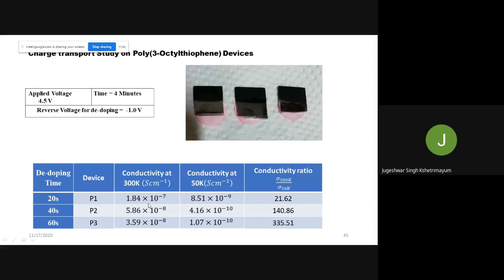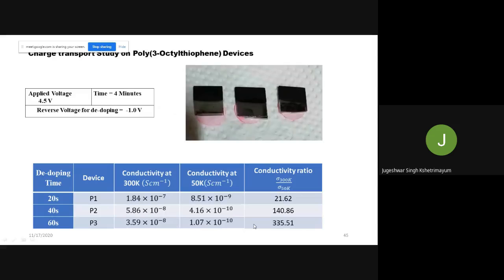Now when I look at the conductivity ratio for P1 from 300 Kelvin to 50 Kelvin, the ratio is 21.62. The variation of conductivity is very small compared to the others. But in the case of P3, the variation of conductivity is very, very high. So what does this mean? This says that a thermally activated process is already involved, which is what we are guessing. Okay, my time is running out, so I'll move a little faster.